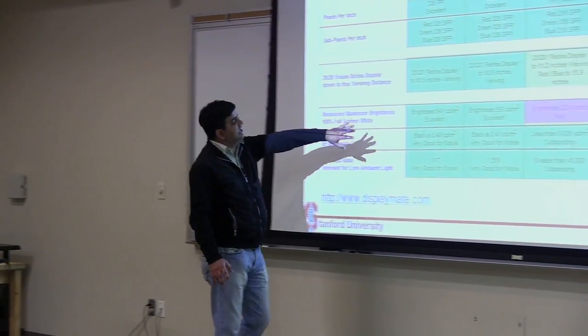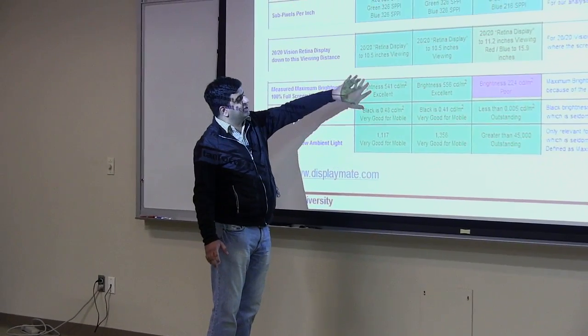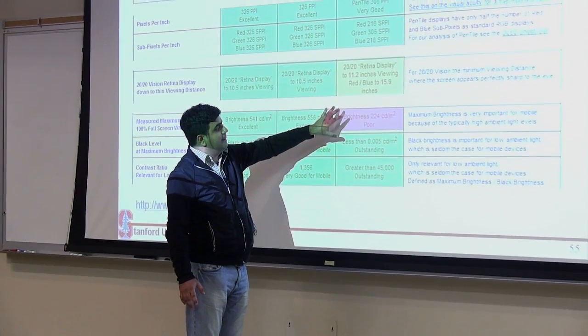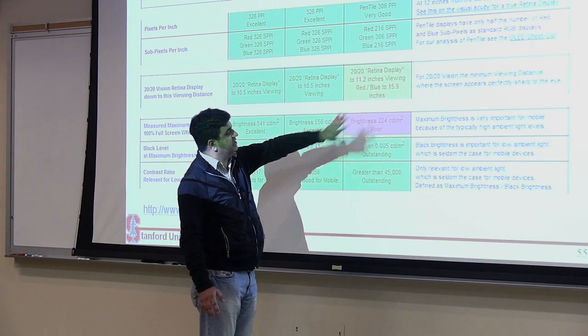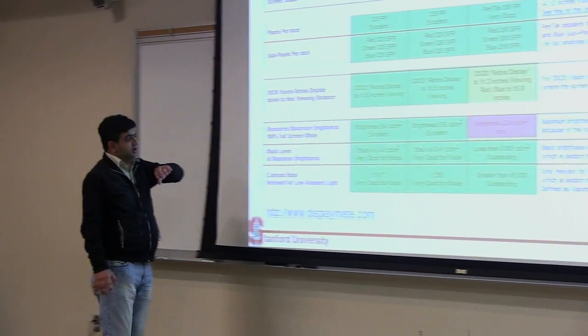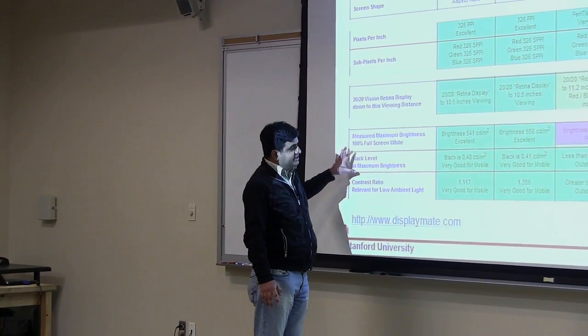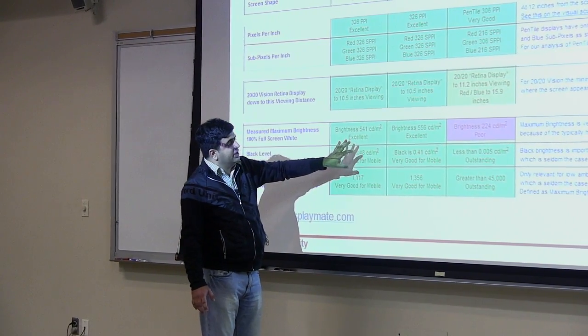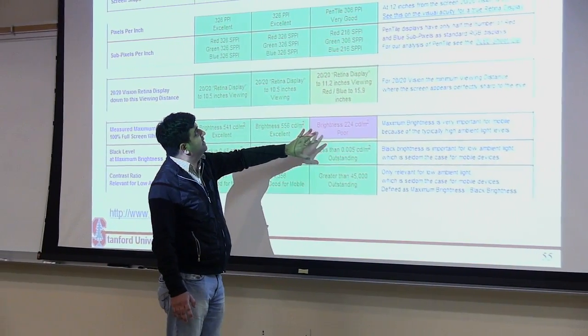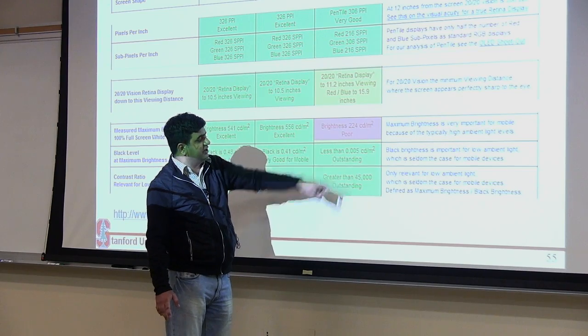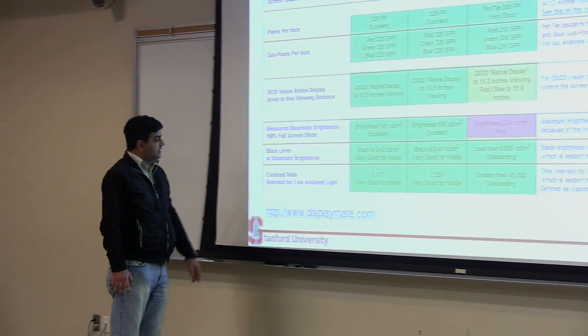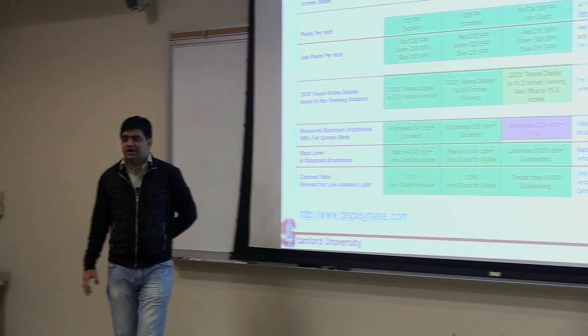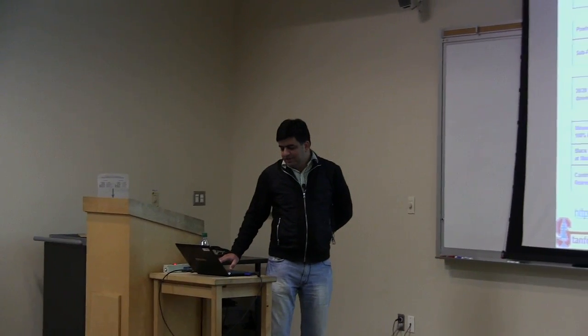Brightness. LCDs are much more brighter, so it achieves brightness of 500 or more. The OLEDs, they are limited by their brightness, by the efficiency of your LEDs, so it has half the brightness of your LCD display. But the black level, look at the black level intensity. Black level intensity in a LCD is minimum of 0.5 candela per meter square. In your S3 which uses the OLED, it's less than 0.005. So black is really black in OLED and that gives you an outstanding contrast of more than what your eye can distinguish. That's a very big selling point of OLED.